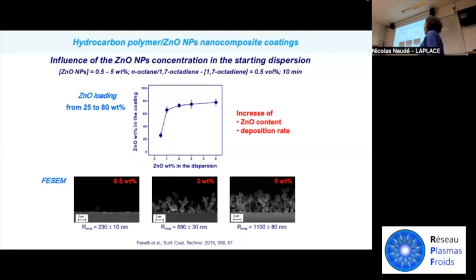This also leads to a considerable increase of the deposition rates. That is, we can really reach thin films with a thickness of even 10 microns with 5-10 minutes of deposition. In such a way, the incorporation of the nanoparticles is really favored in our condition. And as you can appreciate from the SEM images, we can really appreciate the formation of nanostructured, highly porous thin films with root mean square roughness that can be as high as 1 micron and even greater.